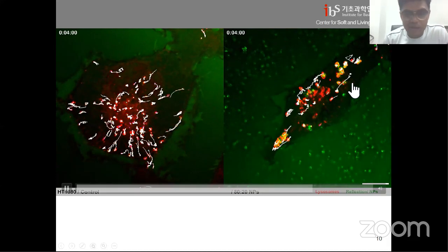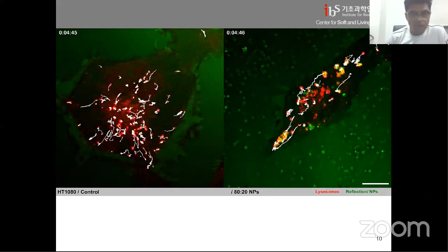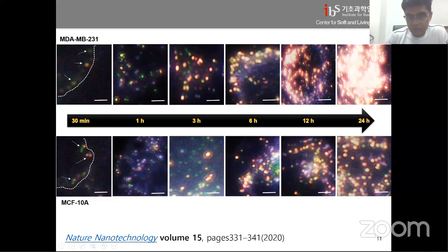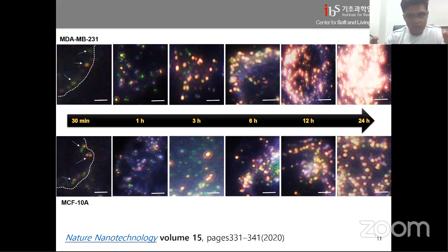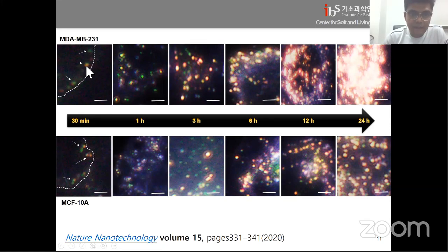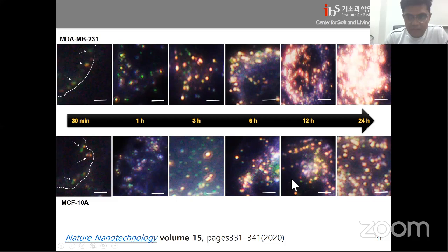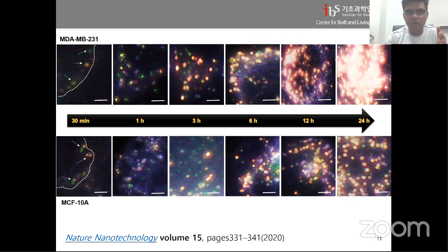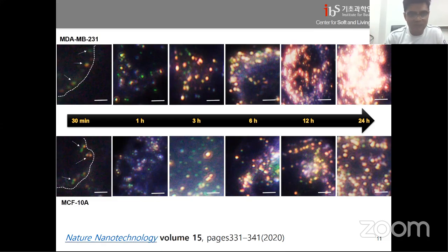We quantified the cluster amounts from dark-field microscopy. When nanoparticles come close together, they scatter light, and the scattering color depends on how close and how much they aggregate. In normal cells, the cluster size does not increase for 24 hours, then cells start secreting the nanoparticles out. In cancer cells, the clusters keep growing until bursting. By tuning the surface charge, we can really impact cell behavior. This paper was also accepted as a cover article, showing beautiful lattice structure formation — crystallization — of nanoparticles inside lysosomes.